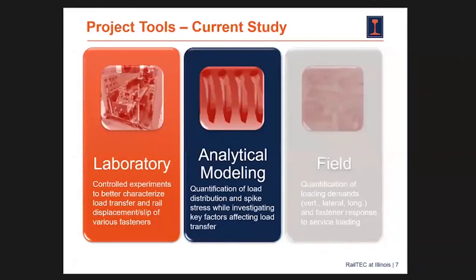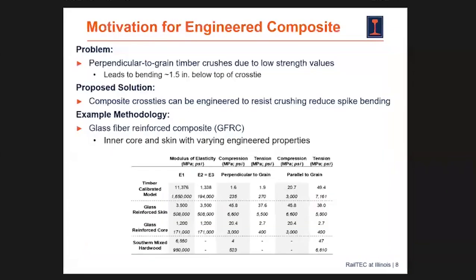And this work was carried out in the lab and the models. Some of the motivation for this came because whenever we were doing our initial modeling, we found that timber ties crush in the perpendicular to grain direction. When I say perpendicular to grain, I'm referring to the direction that's going to be taking these longitudinal loads. It crushes due to these low strength values. And we'll see later on that they're about an order of magnitude weaker in this direction than they are in the long direction, which would be subjected to the lateral loads.